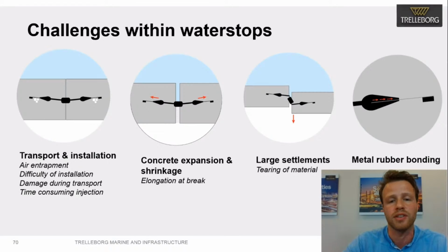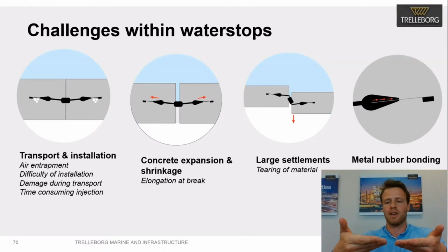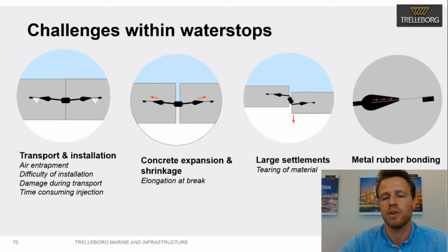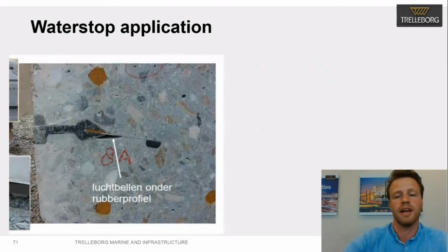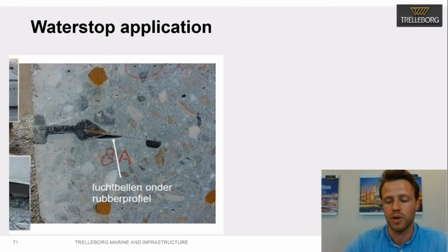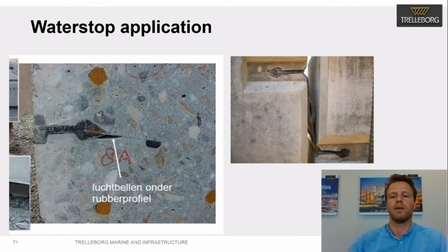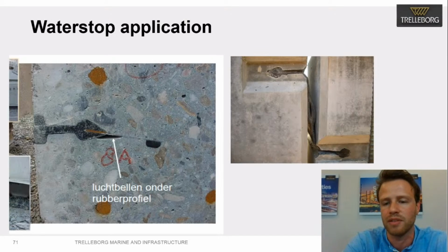During the concrete expansion and shrinkage, you have a lot of elongation, also tensile strength within your Waterstop. As you also saw in the last visual, sometimes there is settlement going on, and you don't want your Waterstop to tear at that point. The rubber-metal bonding is also of importance. It has to do with the tensile strength that acts on this Waterstop, and you don't want your rubber rupturing from your metal. Here you can see an example of air entrapment during the pouring of such a Waterstop, and an example of how a Waterstop can deal with these types of settlements.